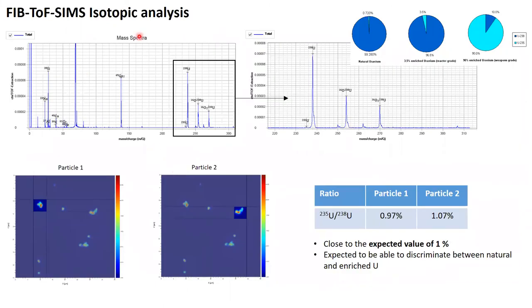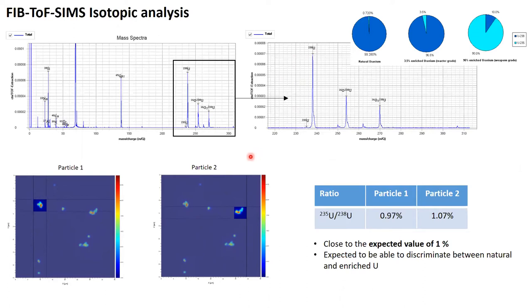In another isotopic analysis example, we looked at very small uranium particles, on the order of just a micron, and analyzed individual particles to determine their ²³⁵U to ²³⁸U ratio. Analyzing a standard with about 1% ²³⁵U to ²³⁸U ratio, we got very close to the expected value — giving us confidence to use the instrument for basic isotopic ratio analysis of uranium. This can also be combined with high resolution imaging and EDS.